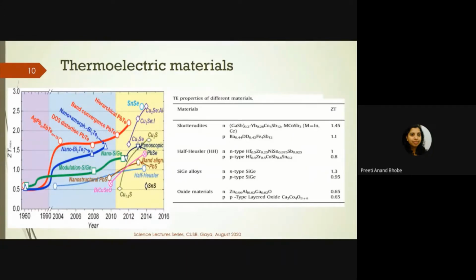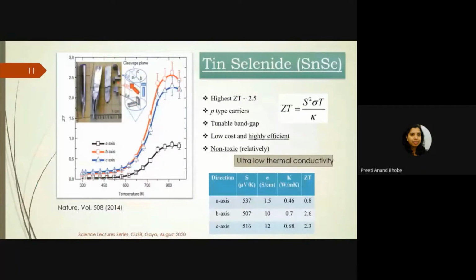Okay. And that tin selenide is why it is a celebrated material. It was published in Nature in 2014, and it showed a ZT of around 2.5, which is the highest ZT known till date for thermoelectric materials, the highest figure of merit. So the question was, why does this material have such a high ZT?